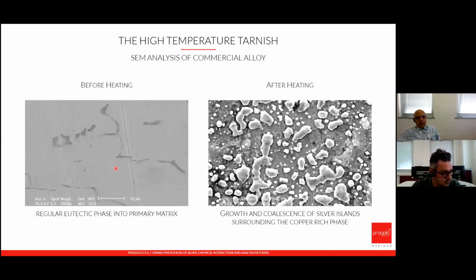And another surprising result came from commercial alloys, where the thermo-oxidation test provided the formation of very silver-rich islands around the copper-rich phase. These islands can also be considered almost pure silver.